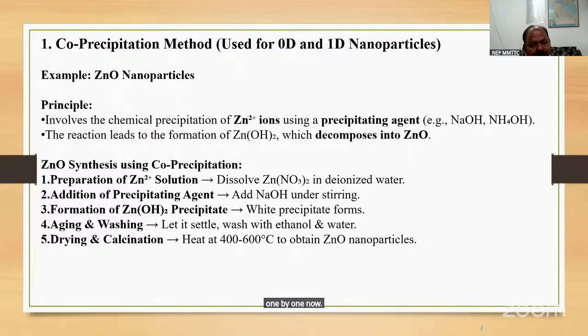One by one now. Co-precipitation method, and this method is specially and particularly used for the synthesis of 0 and 1D nanomaterials, nanoparticles. That is, this method is used for the synthesis of particularly zinc oxide nanoparticles. The principle here is that it involves the chemical precipitation of Zn2+ ions using a precipitating agent, that is sodium hydroxide or NH4OH, and this reaction leads to the formation of zinc hydroxide, which decomposes into ZnO.